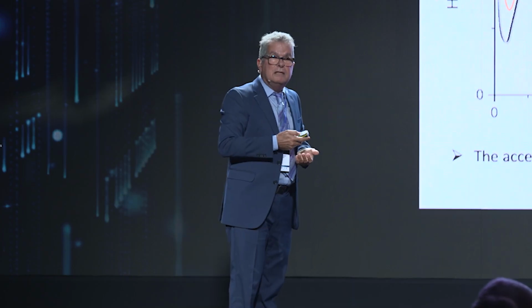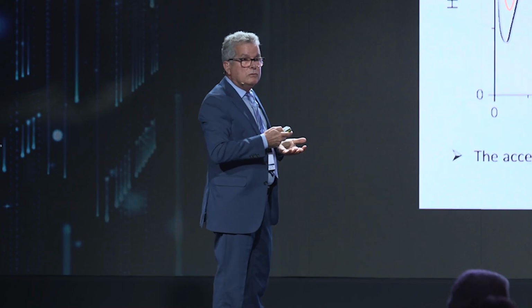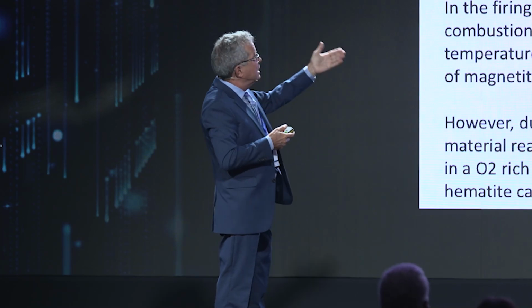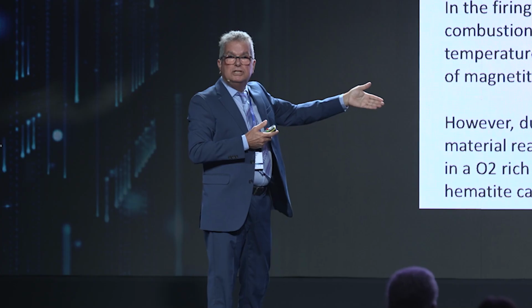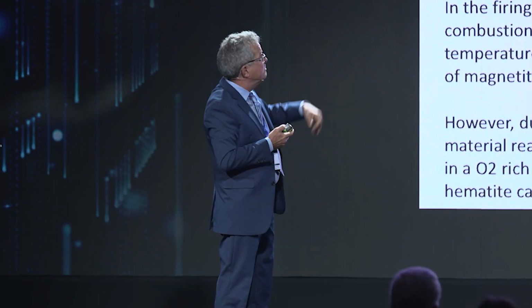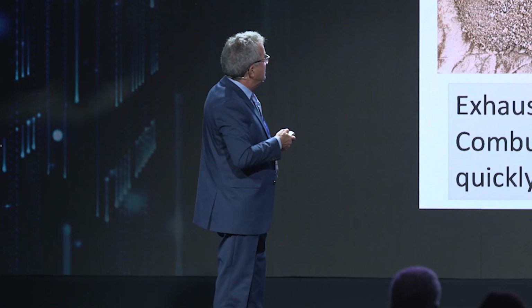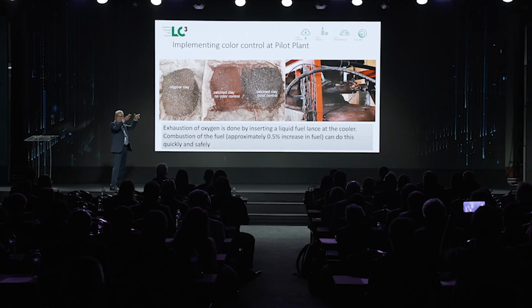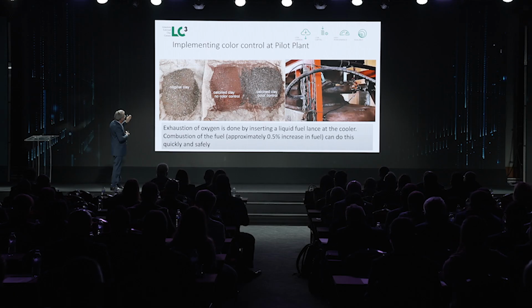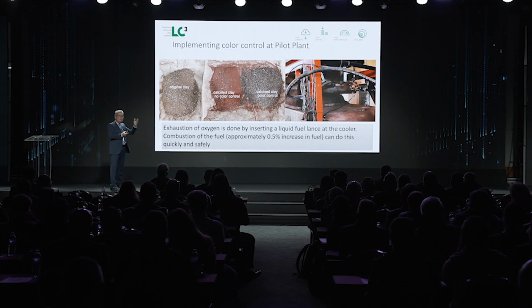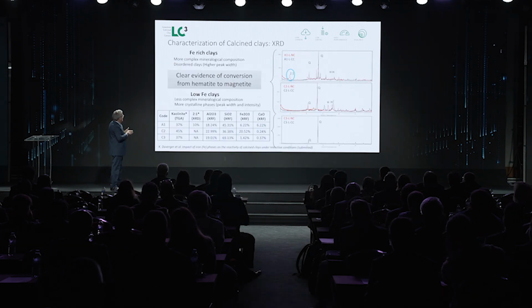But okay, I understand the point that many people don't want to have a red cement. So what you can do is you can control the cooling conditions in the system. This is also a paper I published on that. And in practical terms, what you have to do is in the cooling chamber to introduce or to find a way to do the cooling of the system in a reducing atmosphere, so that you can have different phases of iron, either hematite, which is red, or magnetite, which is black. We have clear evidence of that doing the test.